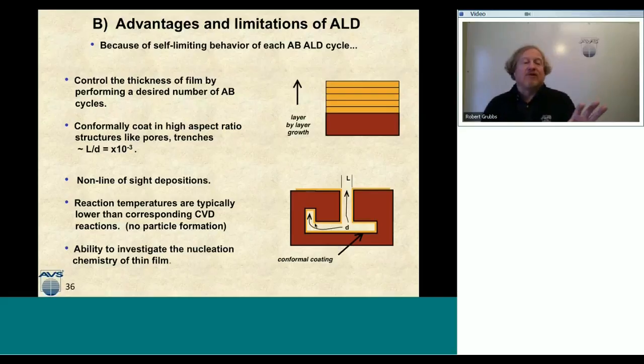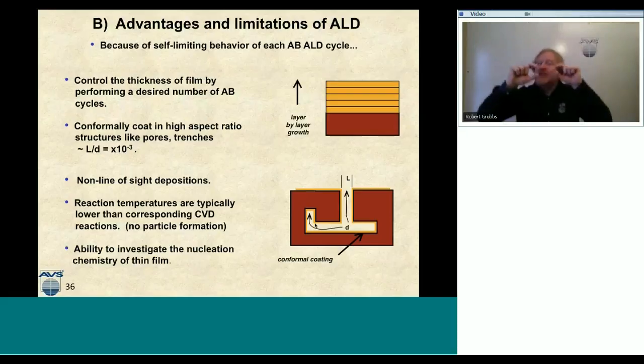It also produces no particles, whereas in CVD, those chemicals are reacting on the hot substrate or in the near surface region, and if they don't get deposited on the surface, then they'll generate particles in the reactor. And if you talk to anyone in the semiconductor industry, particles are really sort of the bad news, and they're difficult to get rid of. So in these ALD chemistries, we really don't have any particle formation as long as our pulse and our purge steps are an adequate length in order to sweep all the precursor out.